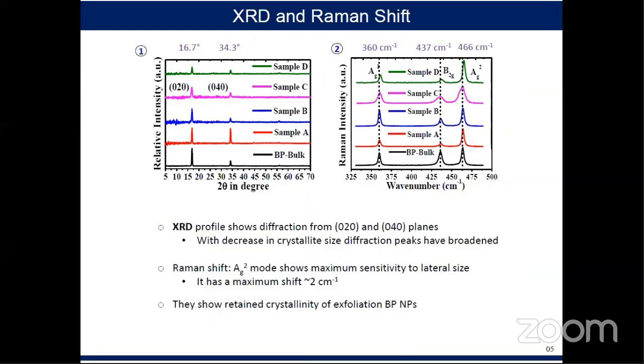Next slide. We then characterized the structural and chemical stoichiometry using XRD and Raman spectroscopy. In XRD, I have compared the various sample XRD spectra with bulk. As the crystalline size goes down, the XRD peak has diminished intensity, and the peak has also broadened a bit.